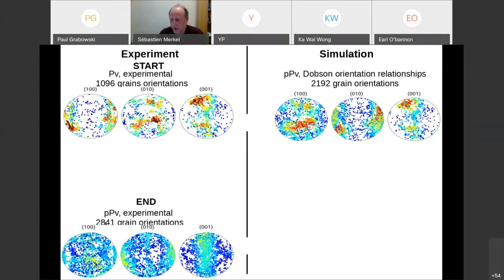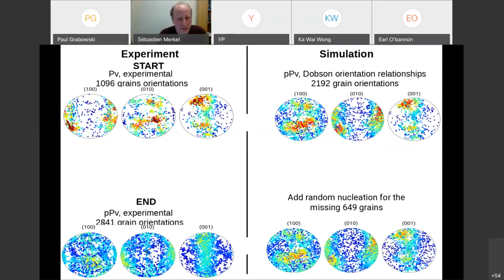And if you look more carefully, we have 2,200 grains in the simulation. We have 2,800 grains in the experiment. And so those grains have been coming from somewhere. And I think they've been nucleating randomly from the powders that's floating around the sample. And if you add 649 grains, which are the missing grains, if you do just the counting, you add them randomly into your simulation. This is the simulation. This is the data. So there is a very, very good match between the data and the simulation, and so it's very consistent with the mechanism of transformation between perovskite and post-perovskite that was suggested by David Dobson.